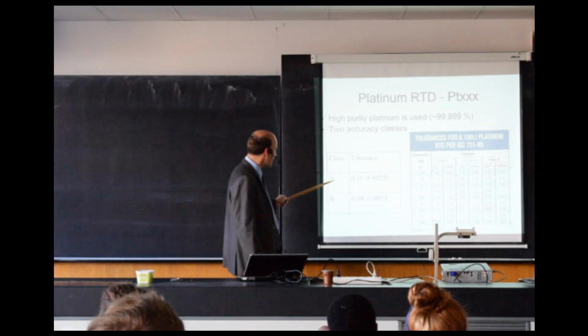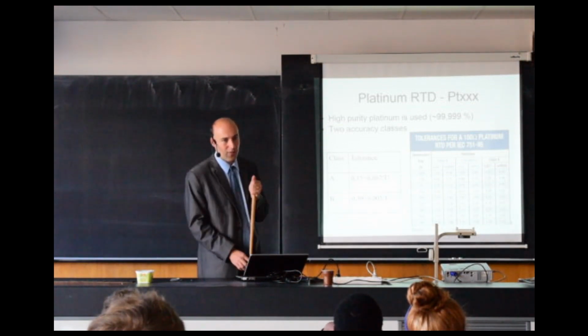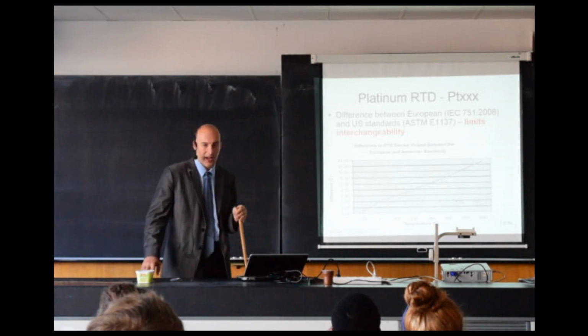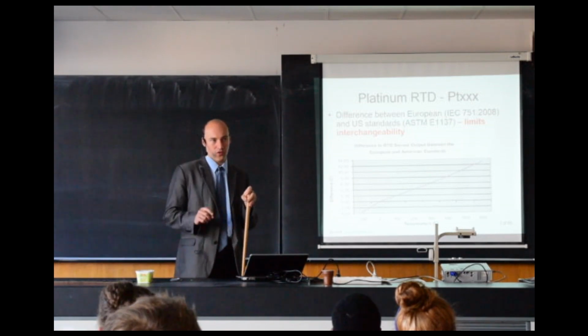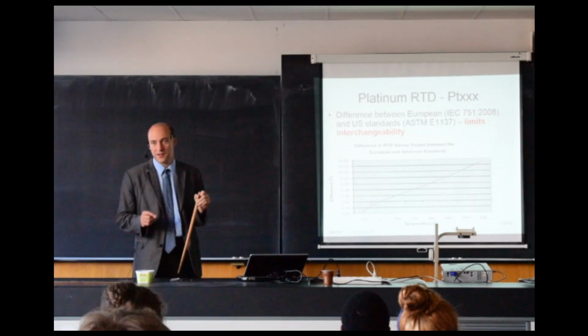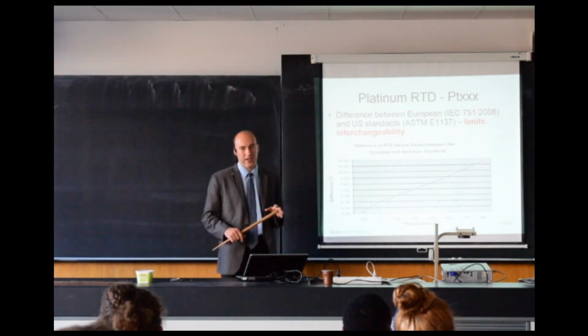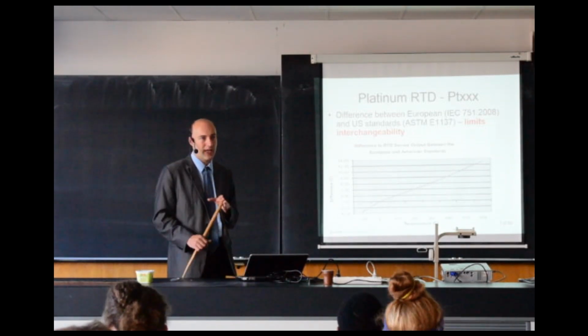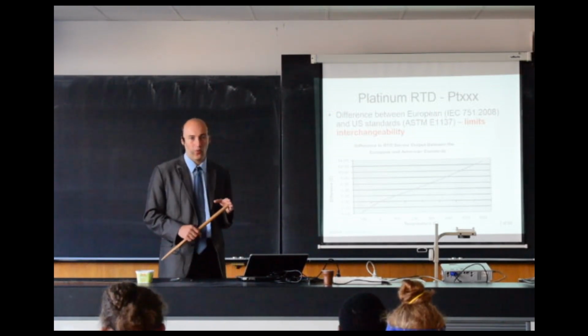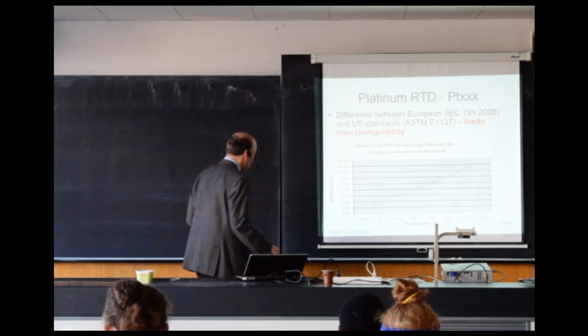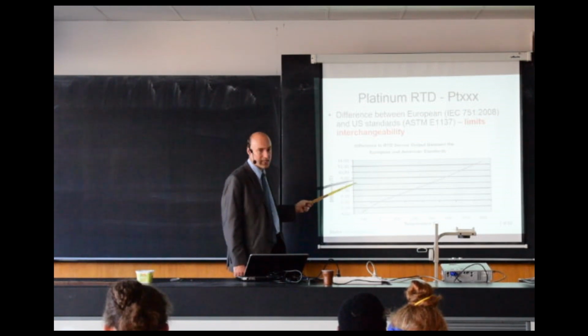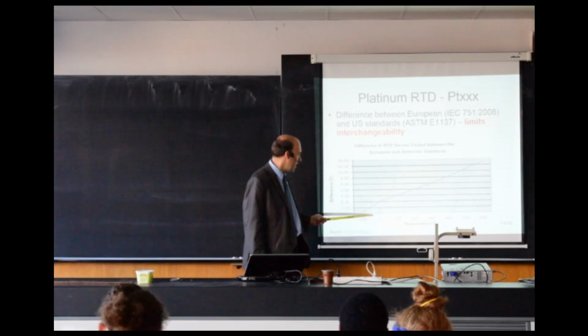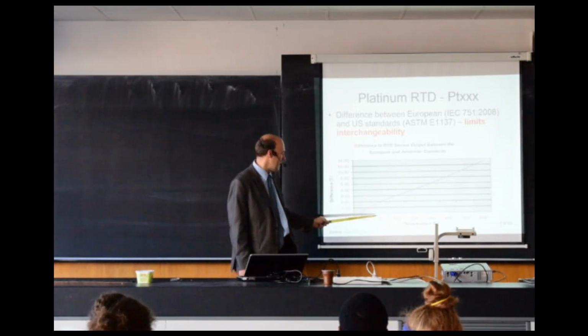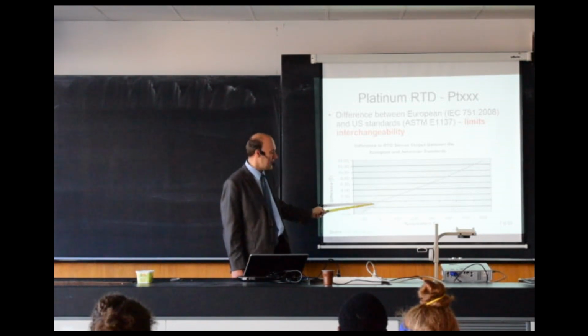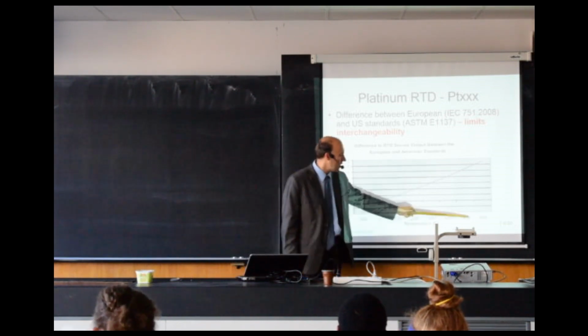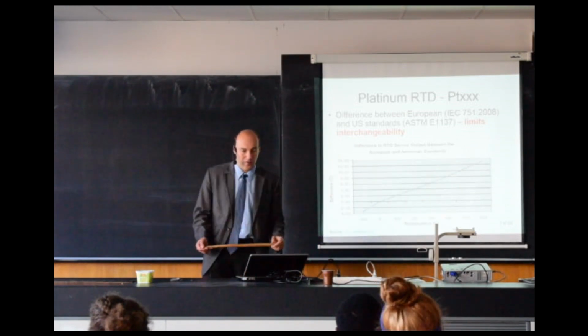Unfortunately, the tolerance classes and the degree of purity of platinum are different if you follow the European and US standards. So you need to be very careful which standard you choose. This is not to say that one standard is better and the other is not. This is just saying that if you have your application calibrated for a specific PT100 from one standard, and you replace that for some reason with another one, then you may have problems in accuracy. In this chart, you see the difference in degrees between the European and the US standard. So for 0 centigrade, they all have 100 ohms precisely. So the difference, the error that you make, is 0. So here it's fine. But for example, if you look at 600, then the difference is roughly 13 centigrades.